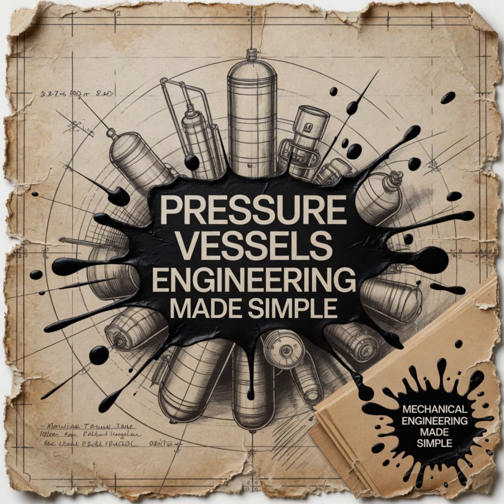But fracture mechanics steps in and reveals the trap. The paradox is this. As you increase the yield strength of a steel alloy, you almost always decrease its fracture toughness. Right? Yes, you're trading ductility for raw strength. The metal becomes much harder, but it also becomes stiffer and far more brittle. It's like trading a flexible climbing rope for a solid steel cable. The cable can technically hold more static weight, but if there's a sudden jerk, the rope stretches, while the cable might just snap. That's a great analogy.